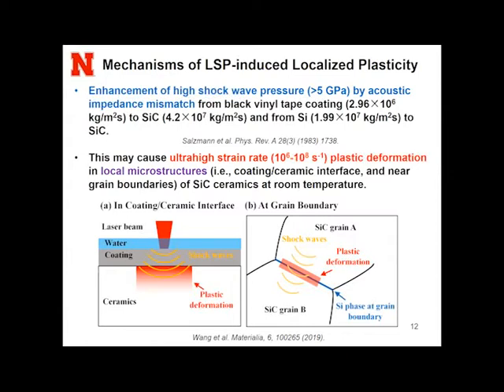when the shock wave generated by LaserShock peening propagates across an interface, it can be enhanced, because some shock wave is reflected back, and the shock wave pressure at the interface is enhanced when the different materials have different acoustic impedance. We use this phenomenon to explain our case, because the shock wave will transfer from the vinyl coating to the ceramic. So near their interface, there could be some enhancement of shock wave. And in the second case, the grain boundary of the silicon carbide contains some silicon phase. So the acoustic impedance mismatch between the silicon carbide and silicon can also generate some local enhancement of shock wave.